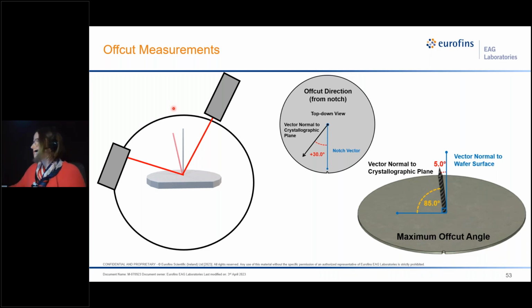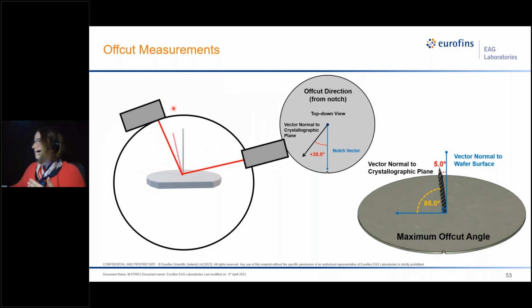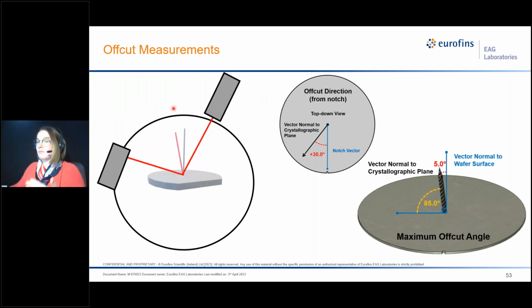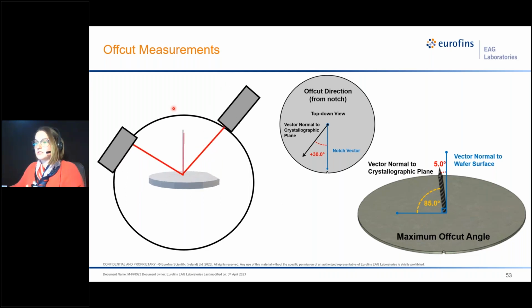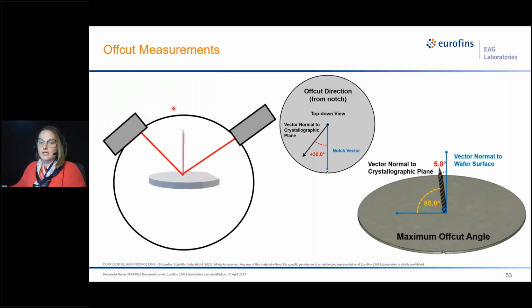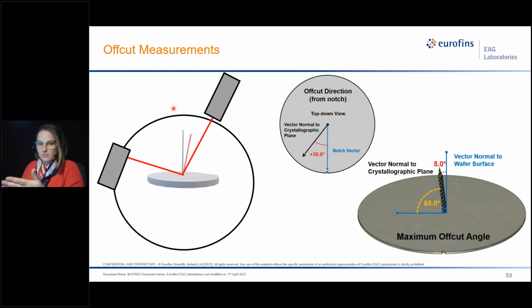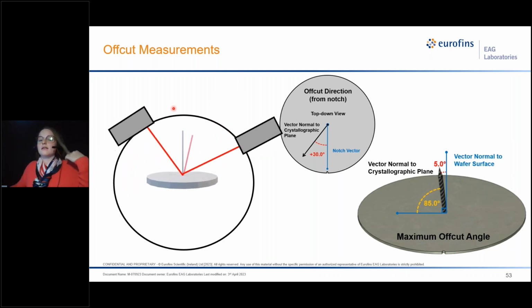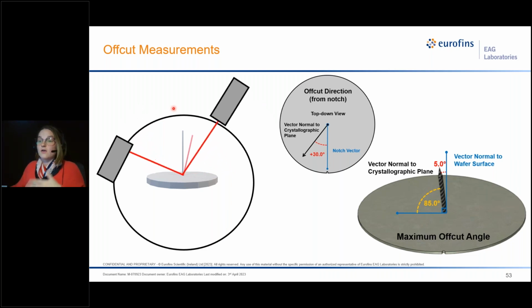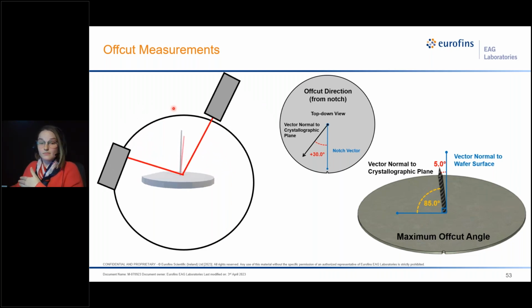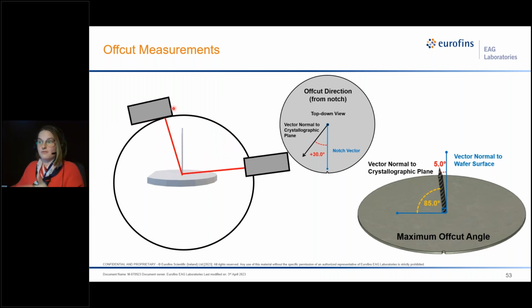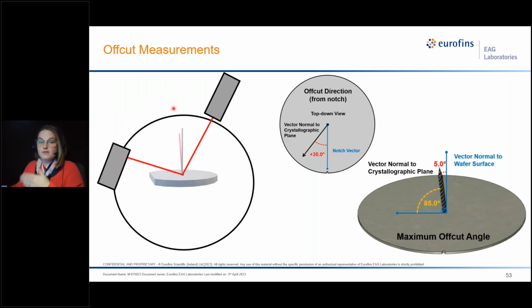And so in order to measure an offcut, we essentially are going to do omega scans at different phi. So what that means is that with these 4 measurements, you can determine what your offcut is and also in what direction on the wafer that offcut is from. Now, again, if your wafer has a notch or a flat, we typically use that as the direction of the offcut from that reference point. But if you don't have one of those, the reference point is what you choose it as, and then we, again, can tell you the direction of where that offcut is from.